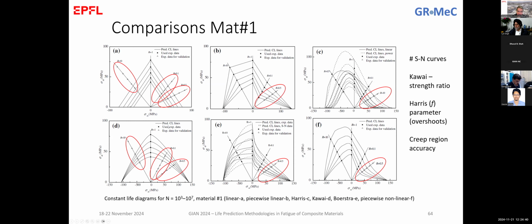The same for Kawai, where I used only one SN curve, this one that is the critical ratio, if you remember that we mentioned. And then I predicted the other 3. And we see that the prediction here is very, very poor for this material system. The same happens for the linear diagram. I used this one to predict the other 3, and the prediction is, as expected for the linear diagram, not good at all.